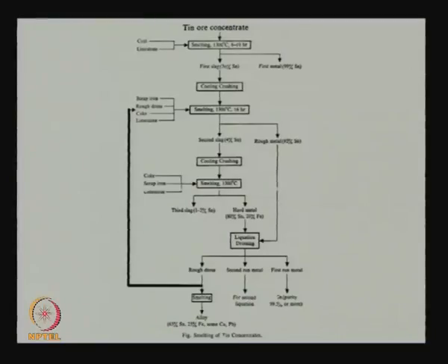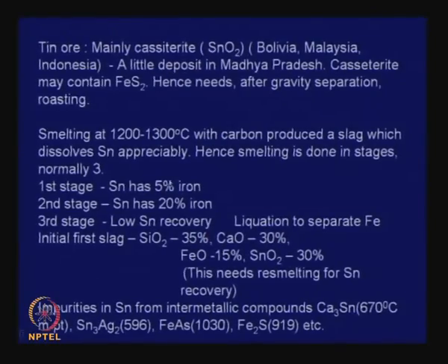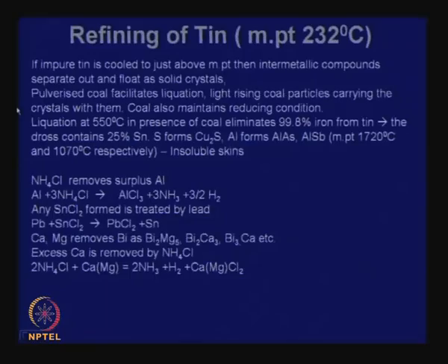Tin melts only at 232 degrees. So, we take the impure tin to slightly above the melting point. You have now a molten mass. Inside, the impurities that we have as intermetallic compounds have higher melting points. Remember, I have shown them. You see at the bottom of this slide, you have Ca3Sn at 670 degrees. You have an intermetallic compound with silver at 596, FeAs at 1030, Fe2S at 919. So, there are these impurities which are very high melting.